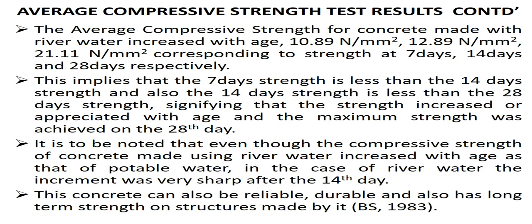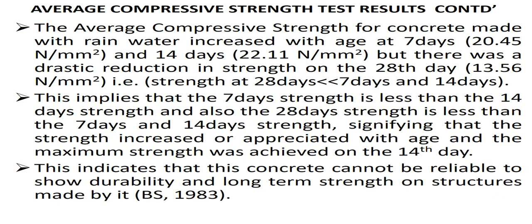28th day. It is to be noted that even though the compressive strength of concrete made with river water increased with age as that of potable water, in the case of river water, the increment was very sharp after the 14th day. This concrete can also be reliable, durable, and has long-term strength on structures made with it. The average compressive strength for concrete made with rainwater increased with age at 7 days, that is 20.45 Newton per millimeter squared, and 14 days, that is